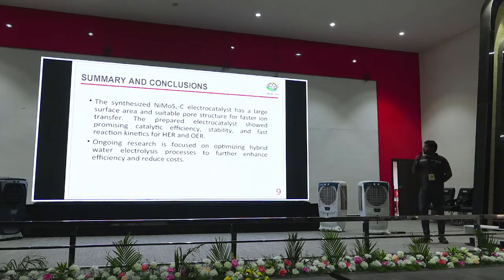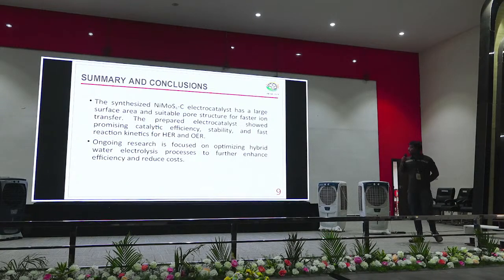Summary and conclusion: the synthesized nickel molybdenum sulfide electrocatalyst has a large surface area and suitable pore structure for fast ion transfer. The prepared electrocatalyst showed promising catalytic efficiency, stability and faster reaction kinetics for HER and OER. Ongoing research is focused on optimizing the hybrid water electrolysis process to further enhance the efficiency and reduce the cost.